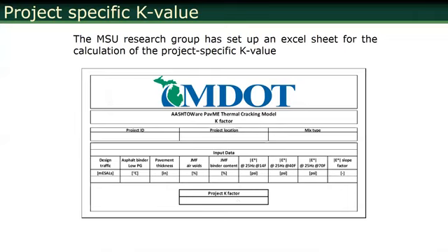Where would you get the E star from? A prior mix design? Yeah. For MDOT we tested 64 different mixtures, collected all over the state on MDOT projects. So 4E, 3E, 5E, a whole bunch of projects, and MDOT actually came up with default, approximate E star values for different 4Es and 5Es with different PGs and everything.